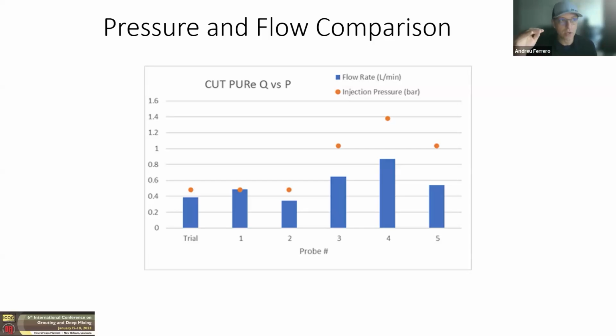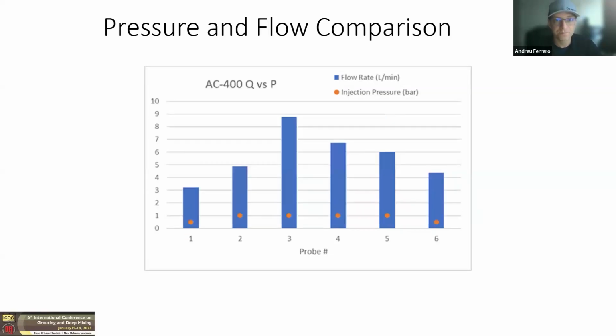up to a certain point where that injection pressure goes up to a fracture point, where then you fracture the soil with the pressure from the grout, and then your flow rate will greatly increase, because now you have an open path for that grout to flow. And that's what we're trying to avoid in permeation grouting, is that fracture pressure.